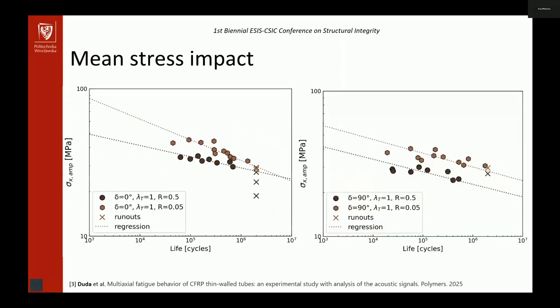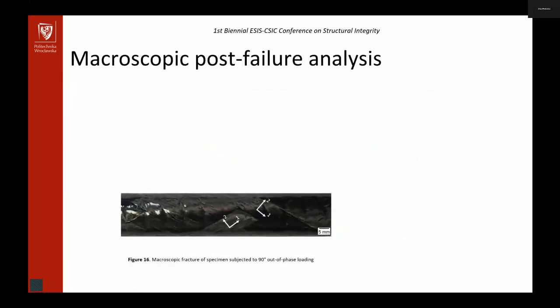And so, same as before, if we consider the positive load ratios, in-phase and out-of-phase load, we see that the fatigue life differs if we include the mean stress. So for higher mean stress, the life is lower in both cases, for in-phase and out-of-phase loading. So we have the fatigue experiments, the S-N curves.